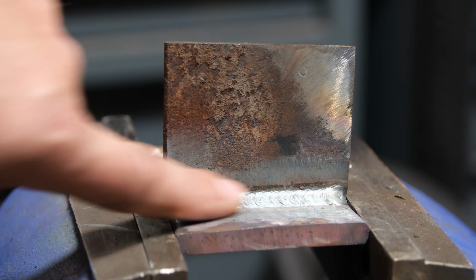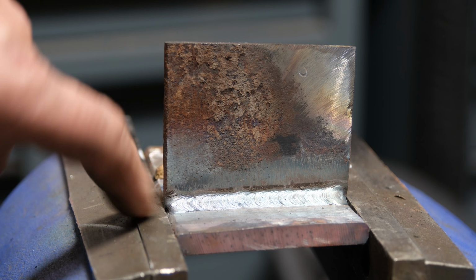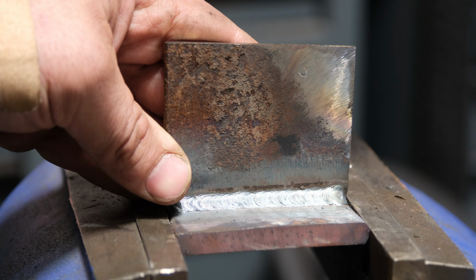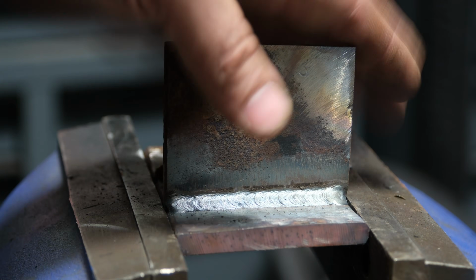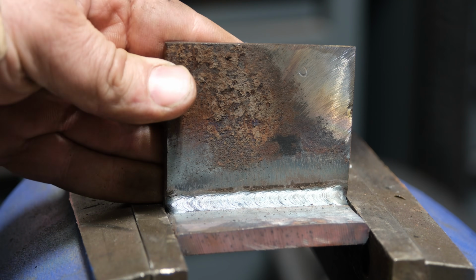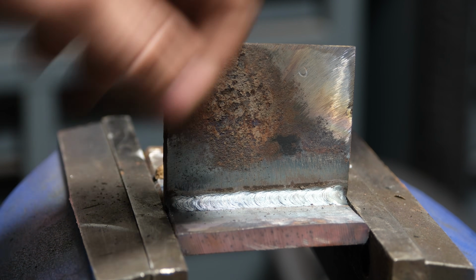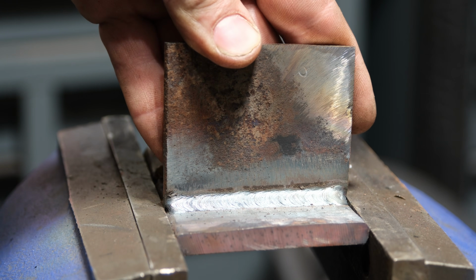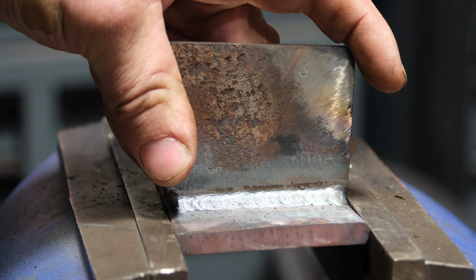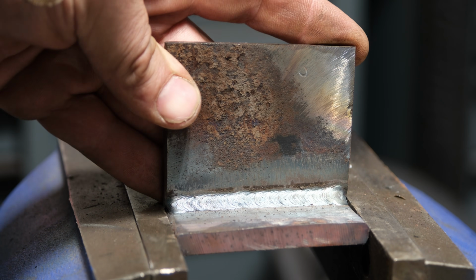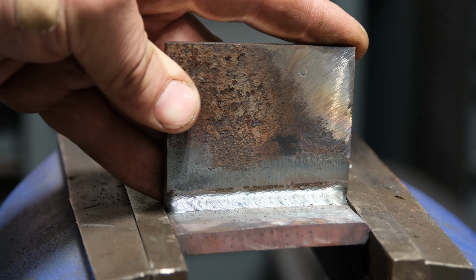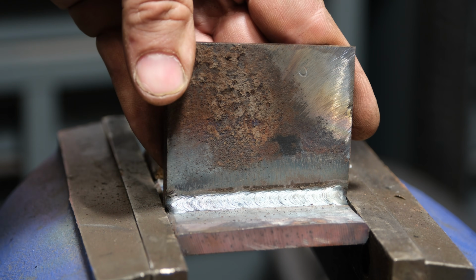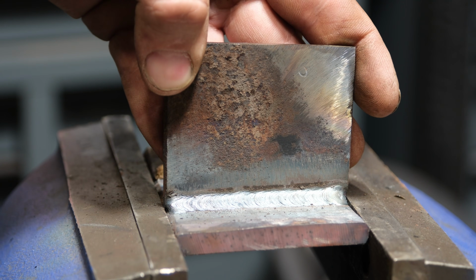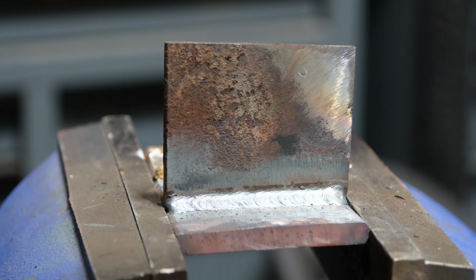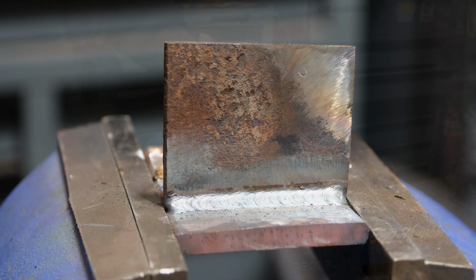So I chipped the slag off of this and everything looks really good. This weld is pretty much defect free. As you can see, it has cooled down a lot. It took a long time for this to cool because of how thick this was and how hot the preheat was. But for all practical purposes, we're in the same boat we were before. The only difference is that we did a backyard, backwoods heat treatment on it. So let me zoom out and let's hit this with a hammer and see what we got.